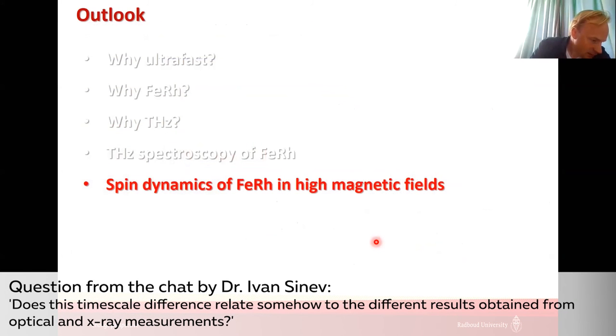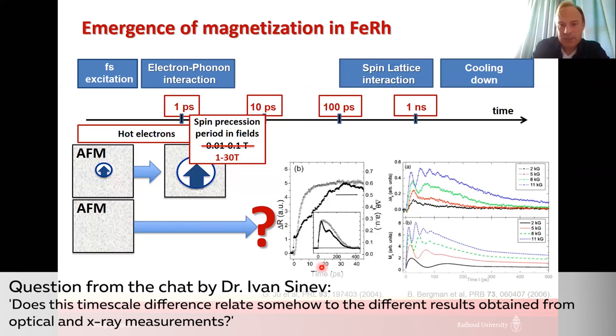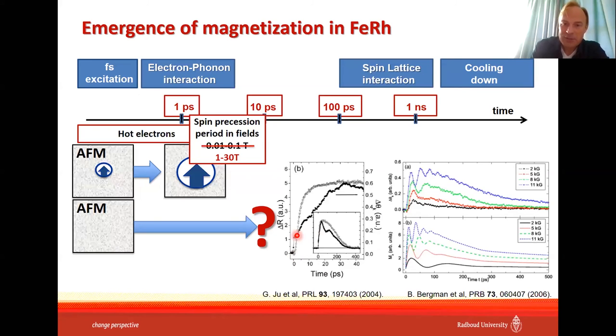So does this timescale difference relate somehow to the different results obtained from optical and X-ray measurements? Now, you see here in optical measurements, they applied a very small field and they claimed the first ultrafast change of the magnetization, which can be observed only if you apply a magnetic field. If you see a picosecond change of magnetization, you have to have 30 tesla. They didn't have 30 tesla here. They had 300 times lower field. So this ultrafast change cannot be explained by a difference in field. The difference in field could explain only the difference in the rise time, on the timescale of 100 picoseconds.